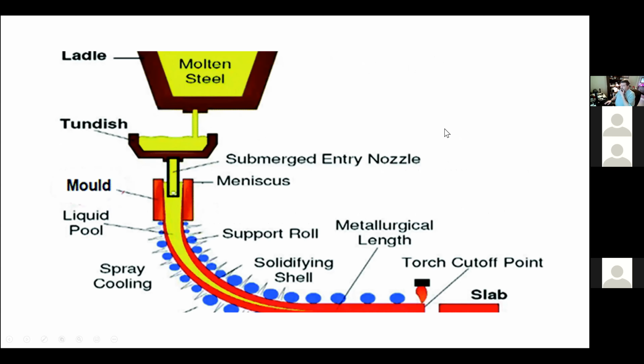So we came up with a number of technologies, which I'll show you in a second. This is just a diagram of a caster. So the steel goes from the ladle into the tundish and then gets poured down into these copper molds, which are water cooled. And so we form a solid shell on the outside of the steel. And then we continue to cool it by spraying water.